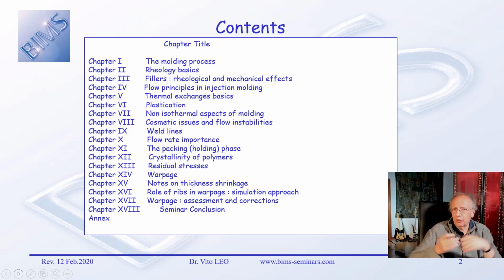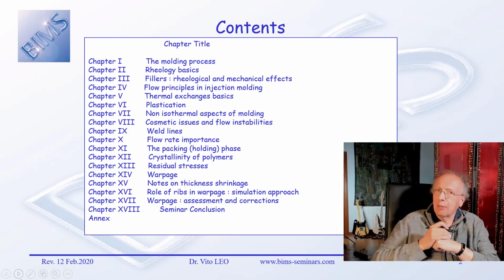Just to mention one of interest, it does happen sometimes when you mold amorphous materials like polycarbonates to observe that the part weight may actually decrease when increasing packing pressure. Now that is something crazy apparently, but it has to do with pressure dependence of the viscosity. Not many people realize that you can literally freeze a polymer by applying high pressure without cooling. At constant temperature you can freeze polycarbonate if you push the pressure high enough.